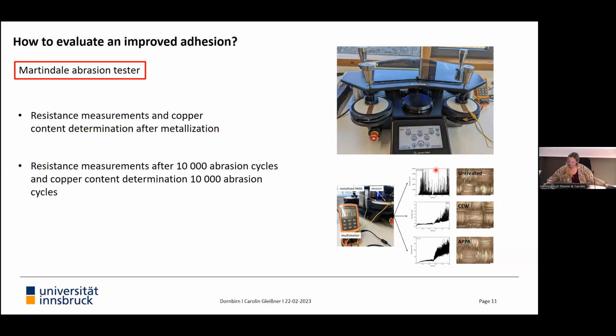And, I mean, it's quite obvious that while abrading the sample, the resistance is also increasing. And you also see that the surface has blank spots of the polyamide fabric where no copper remains on the surface. But the question is now, did my surface treatment affect this abrasion resistance? So now I want to show some results.